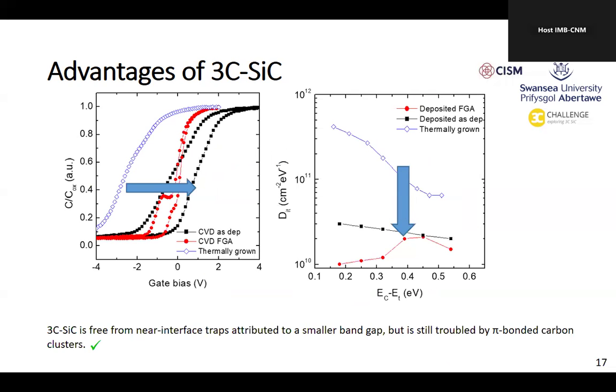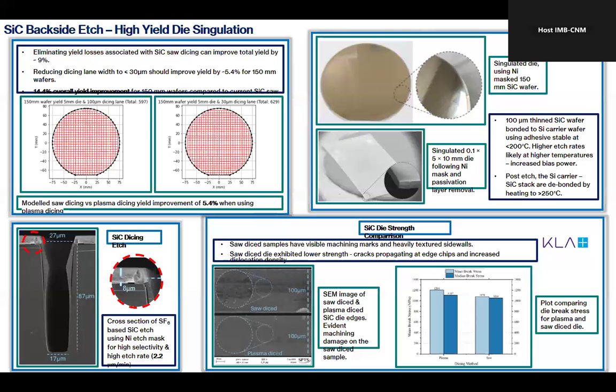And this is some work we did on capacitance voltage analysis, looking at different processing technologies, thermally deposited oxides, and trying to optimize the interface trap density. But look at this, 10 to the power of 10. That's a really low density of interface states. You never see that. I've never seen that in 4H silicon carbide, no matter what. The way this is extracted, I think, was the high-low technique. I can't remember the exact technique, but whatever technique you use, you always saw a lower number in cubic silicon carbide, which is quite unique and quite an interesting prospect for its future. So that's some of the work we did on cubic silicon carbide.